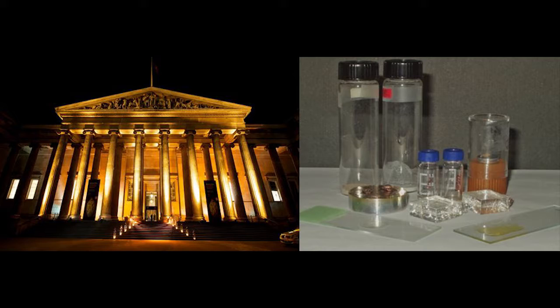And this is the wider operational sequence, if you like, for studying pottery vessels. Sometimes, as was the case with the previous slide, we remove small samples from the inside wall, and on occasions we will drill into the ceramic material itself, on the basis that liquids are likely to have seeped into the matrix of the pot during use. So it is destructive. We tend to take 1 to 2 grams of ceramic material, and these are extracted in the laboratory and then subject to gas chromatography, mass spectrometry, and other analytical techniques.